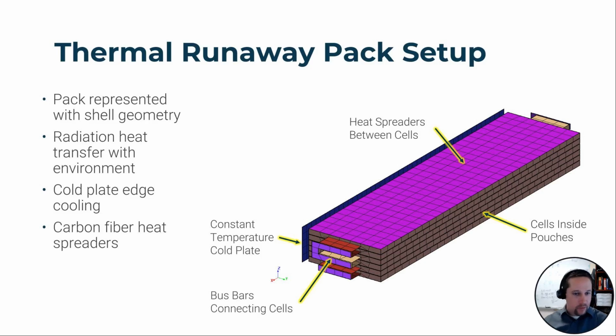And for the case study that we've prepared here, this is a stack up of 6 different cells with carbon fiber heat spreaders between the cells. And it's important to have some kind of strategy to mitigate thermal runaway in this case, to make sure that occupants are safe. Typically, the standard is that the time between a thermal runaway warning sign appearing in a car and the time the occupants have to get out of the car should be 5 minutes or greater.